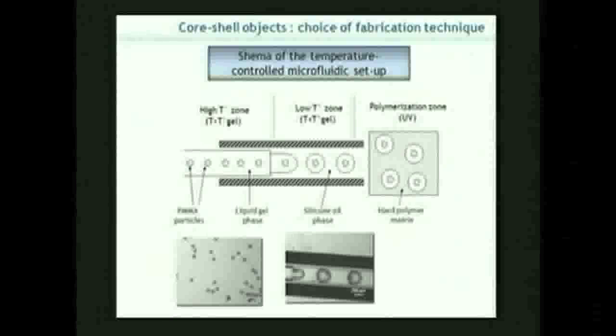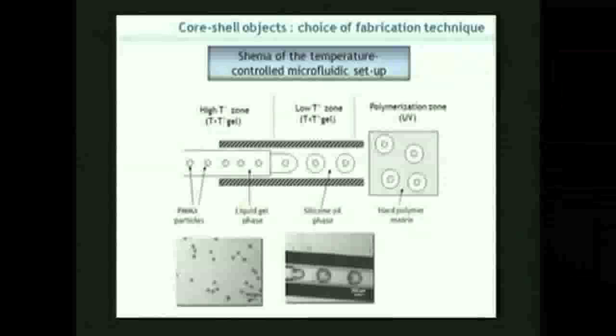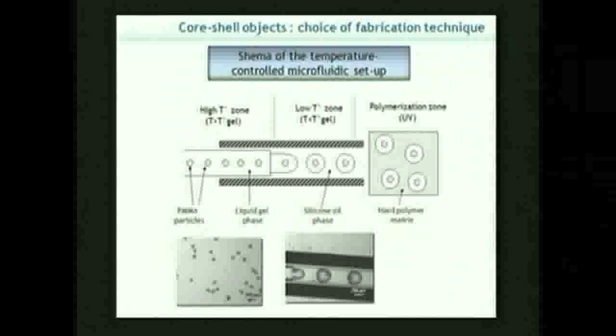So I can encapsulate little particles into larger silicone droplets, and of course the number of objects that I will put in every droplet here will depend on the concentration, on the number of particles that I introduce into the system, and on the difference of speed between the flow in the inner capillary and the flow in the outer capillary. Okay. So you see, these are some pictures here down at the bottom of the slide. You have some pictures of the objects that we are able to make after having found the good conditions for the concentration of particles, the flow inside the inner capillary and the flow inside the outer capillary. Okay?